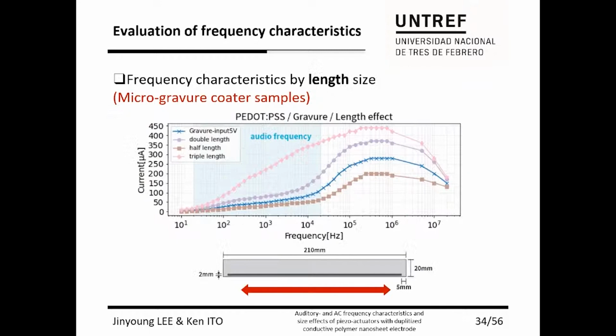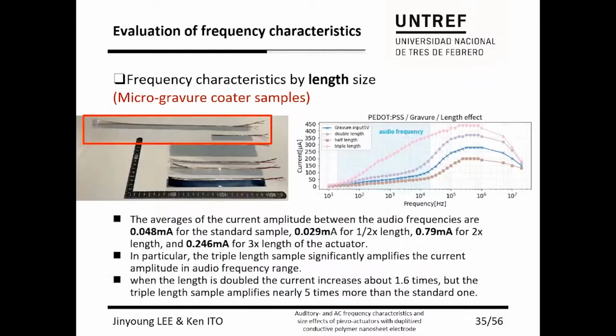Next, we changed the size in the length direction, which is the same as the stretch direction of the piezoelectric film. We prepared half, double, and triple length samples from a standard size. The current response is amplified when the actuator's length is increased. Especially for the triple length sample, the current is amplified nearly 5 times that of the standard size.